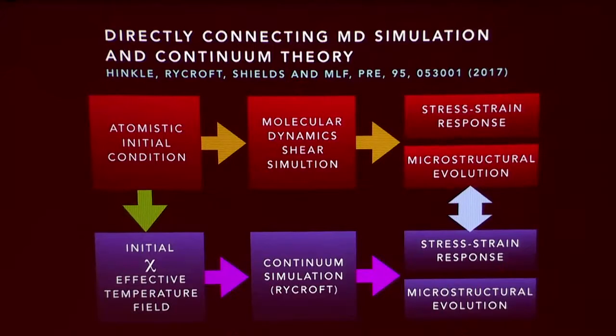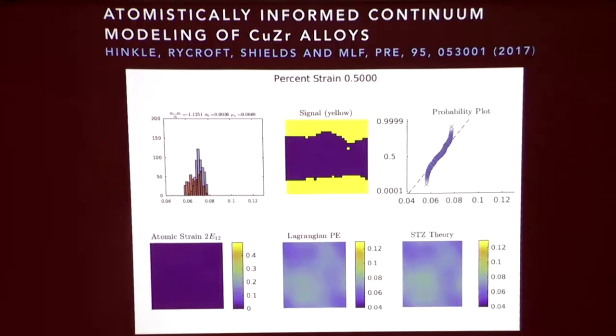Okay, so what I'm going to show you here is one of these simulations. What we've done is coarse-grained the simulation. So here, this is a picture where we've coarse-grained at some length scale. You see these voxels are colored according to whether the local voxel has a strain above the nominally imposed strain or below. So initially, it's sort of just going to fluctuate randomly because you have some elastic waves moving through.